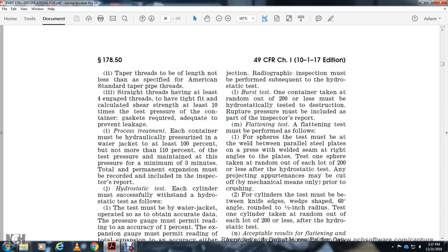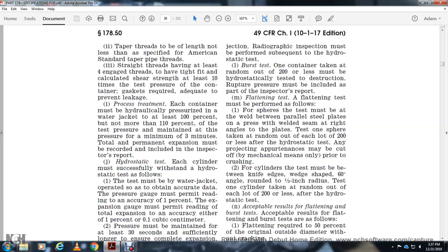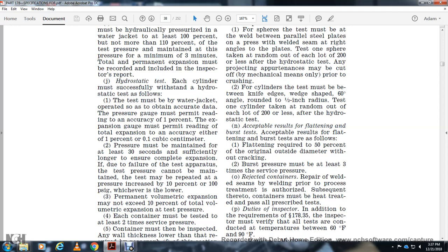The test must be between knife edge wedges with a 60-degree angle, rounded to a ½ inch radius. One cylinder is taken at random out of each lot of 200 or less after the hydrostatic test. Acceptable result of the flattening and burst test: flattening to 50% of the original outside diameter without cracking. Burst pressure must be at least 3 times the service pressure.